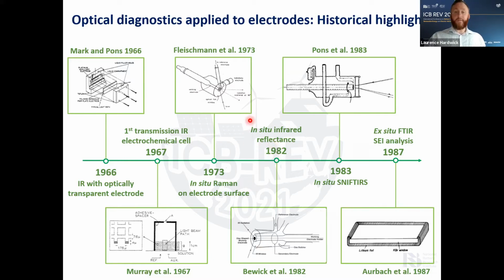Then into the 80s, we have in situ infrared reflectance first demonstrated, and in the following year, using this technique, SNIFTIRS, where importantly there's a Fourier transform to allow much greater sensitivity whilst doing the infrared measurement. In 1987, researchers began to use spectroscopy, particularly infrared, to look at much more complex electrode interfaces. And so for those working in the battery area, you've come across this term SEI, the solid electrolyte interface. This is the layer that forms primarily on negative electrodes, particularly on graphite and lithium, and the intermetallics as well, and it has a very complex composition. It prevents further electron transfer and further reduction of the electrolyte. This is when Aurbach began these studies.